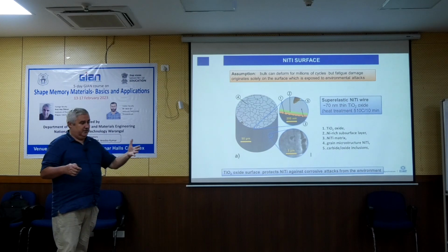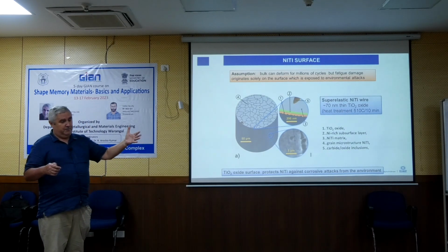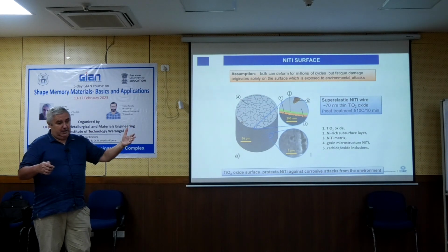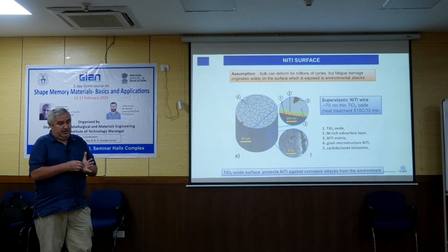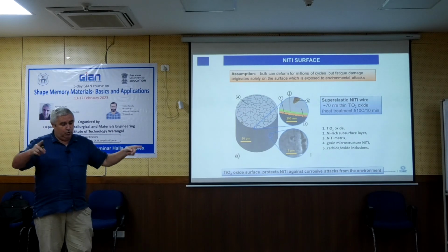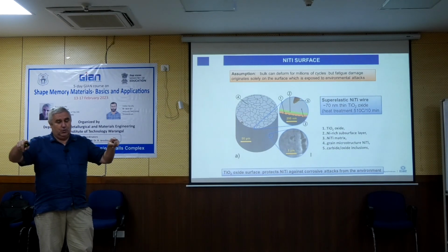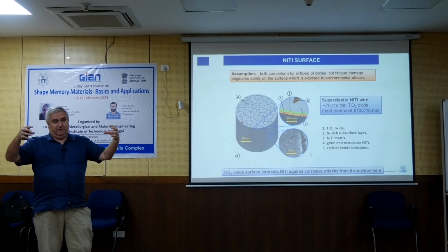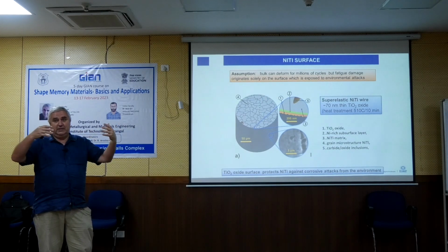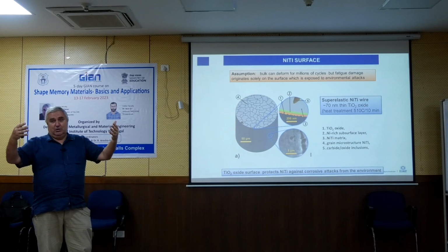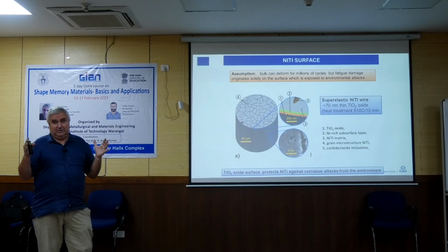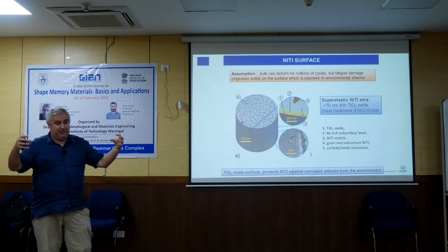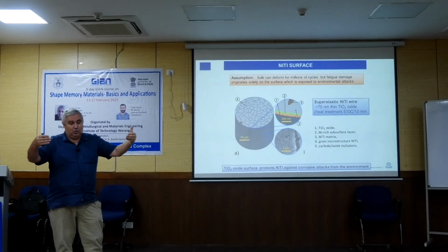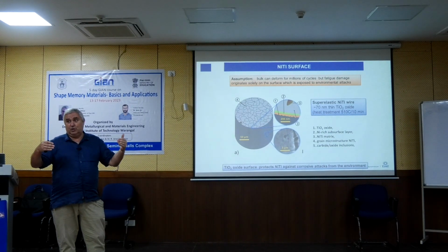Of course, when you buy kilometers of wire on a spool, it is done by heat. When the wire is spooled from one spool to another, it goes through a tube which is filled with a limited amount of oxygen, and it goes through about 2 minutes, and during this time the oxide grows to say 100 nanometer. So the speed of respooling and the temperature and everything is designed not only to control the microstructure of the wire, but also to control the quality and thickness of the oxide.